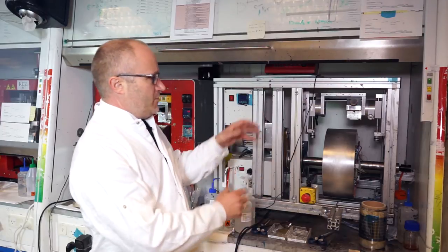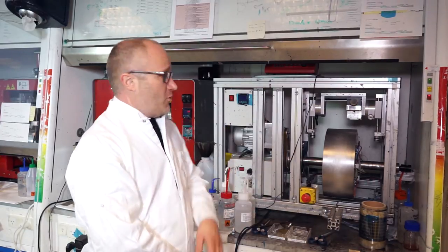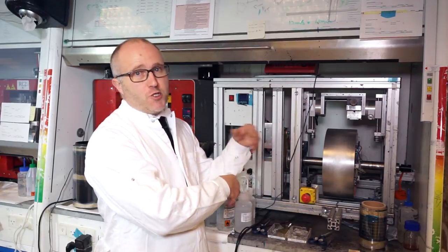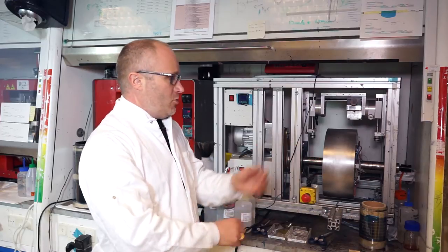Now, in addition to this simple roll, there's a motor on it that allows you to spin the roll. With a web speed that is of course relatively slow compared to industrial high-speed roll-to-roll manufacture, you are limited to web speeds of between 0 and 2 meters a minute. But this is more than plenty of processing window to move from the spin coating environment closer to a roll-to-roll environment, and certainly onto a flexible substrate. And also, in terms of area, a significantly larger area.